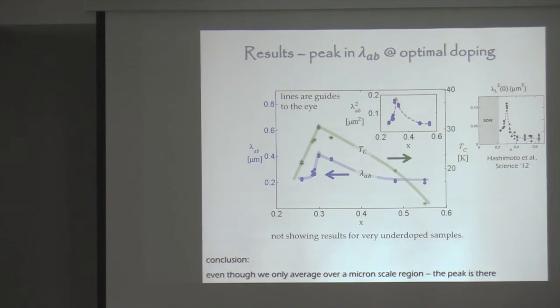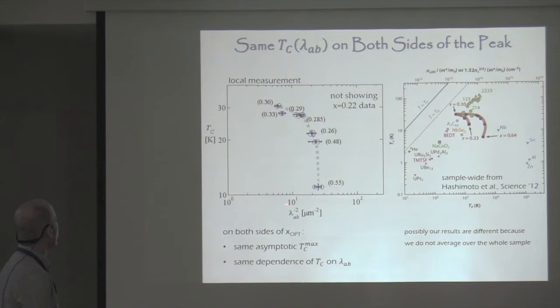And you see that our results are very reminiscent. They basically corroborate this earlier result, especially if we square. So this is lambda squared, so we square it and we get a nicer peak. Another thing that you can do, since we measure lambda and TC at the same point, is plot what's called a Uemura plot. So here's our Uemura plot.